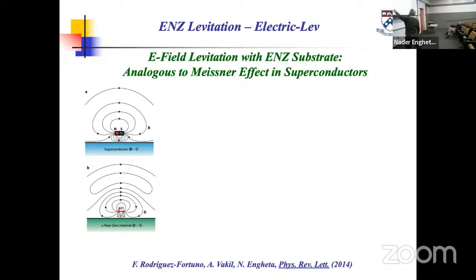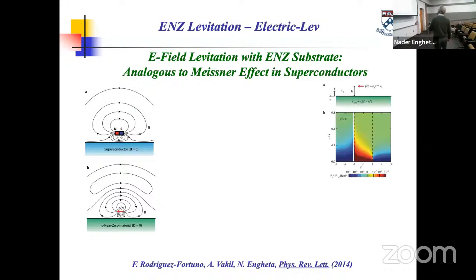So if I have a dipole over here with the frequency omega at which the substrate is ENZ, what happens to that dipole? Can it actually have a repulsive force there? We studied this theoretically, and we came up with this plot that shows the height of the dipole with respect to the substrate as a function of the real part of the permittivity of the substrate. And you notice that the reddish curve shows the repulsive force and the bluish curve shows the attractive force.